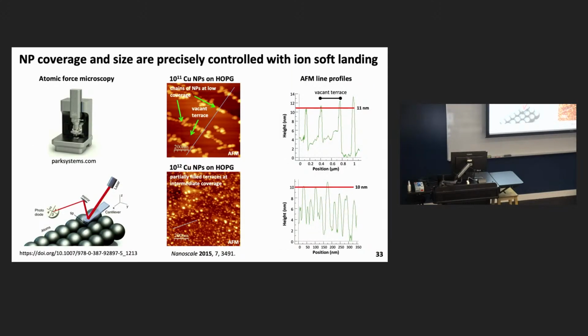So to give you an idea of what these things look like, I have some AFM results shown here in the middle. On the top, you can see what copper nanoparticles look like at relatively low coverage on a graphite surface. One thing that's interesting about graphite is it has this periodic stepped structure.